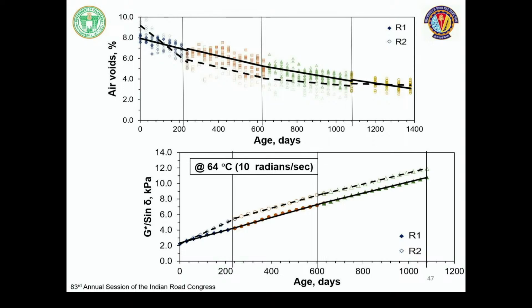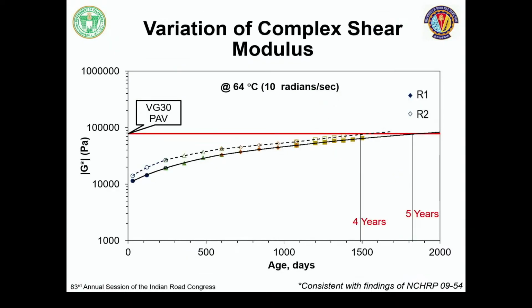So now if I compare between the air voids and stiffness, there is a correlation. Initially the reduction in air voids was significant. Similarly, the stiffness of the binder was also significant. Then it followed a linear trend. And so is the stiffness. When we tested at 64 degrees with 10 radians per second using the DSR, we could predict that around the age of 4 years, it will reach a value equal to that of PAV.